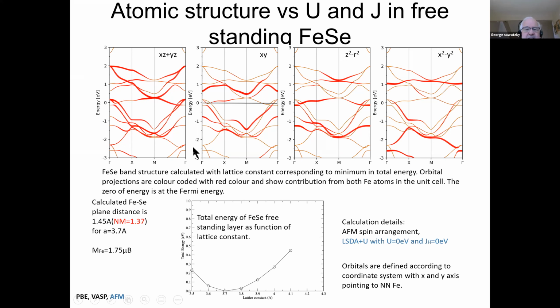So this looks very, very strange. This band structure is completely different now. There still is a hole pocket and an electron pocket, although at the M point it seems that the electron pocket has disappeared and you only have a hole pocket, okay? And you have this strange band, which is almost flat, crossing very close to the Fermi energy. And the magnetic moment is distributed all over the place. It's 1.7 Bohr magnetons. That's what you get at the minimized density functional distance of 3.7 angstroms for the lattice constant, 2 atoms per unit cell, 2 irons.